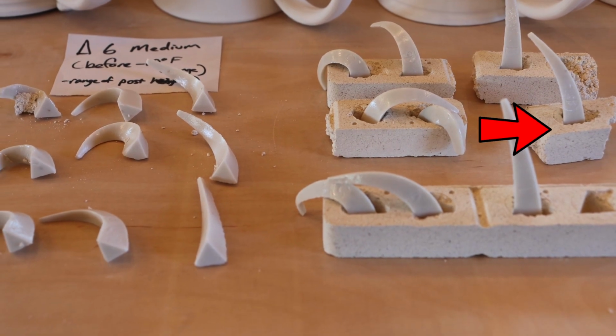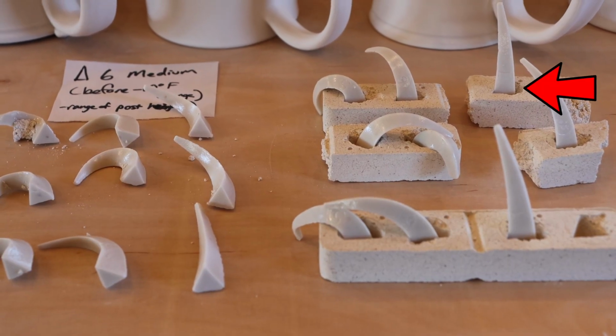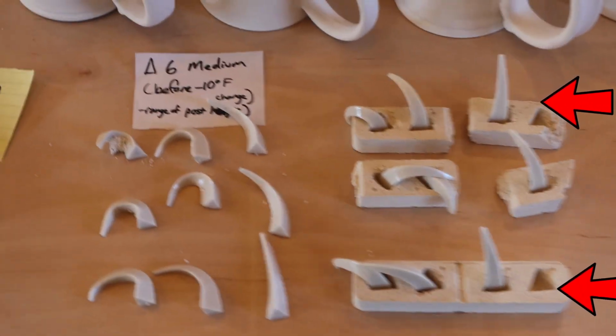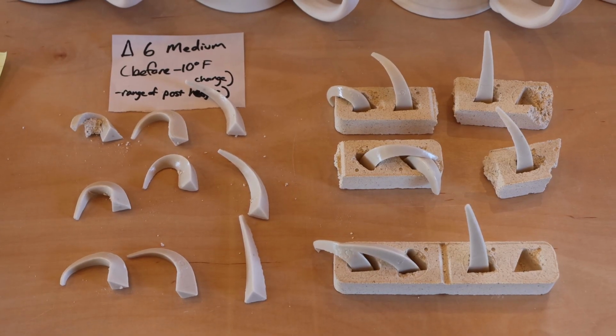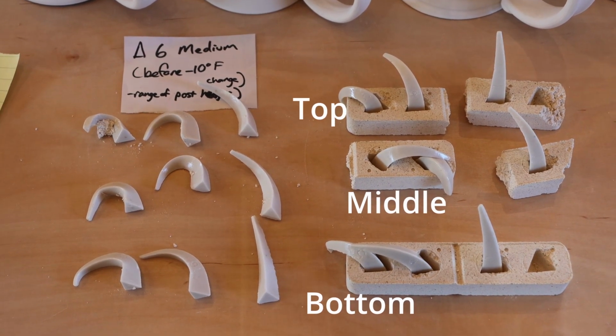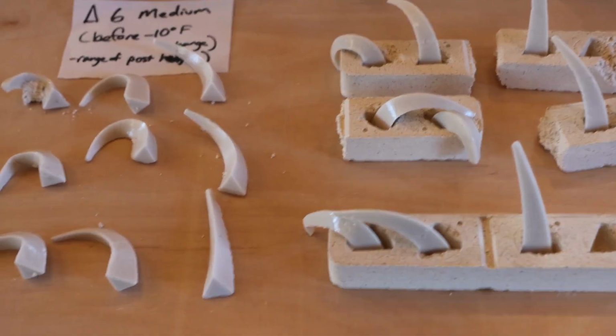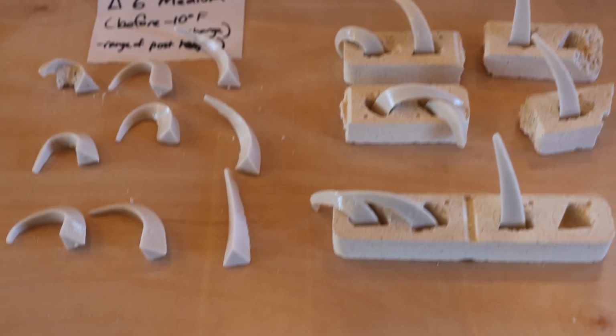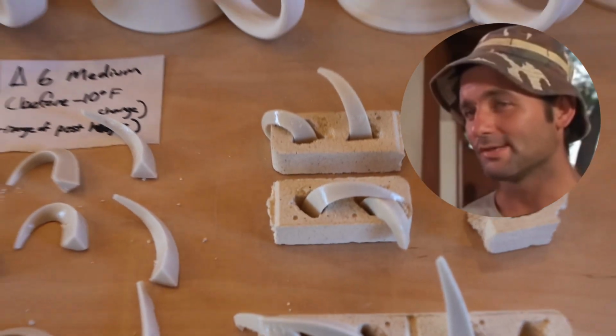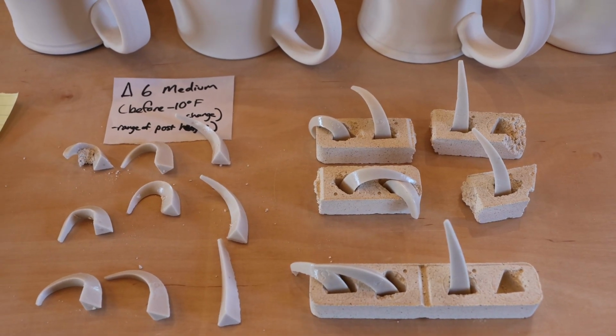The middle one still is bent the most, but the top one looks very close to the bottom shelf now. That's better. Yeah, because the top 2 shelves were really hot. The bottom one was colder. So the bottom really didn't change too much, which is good. Which is nice. And the top 2 seem like we cooled them off.